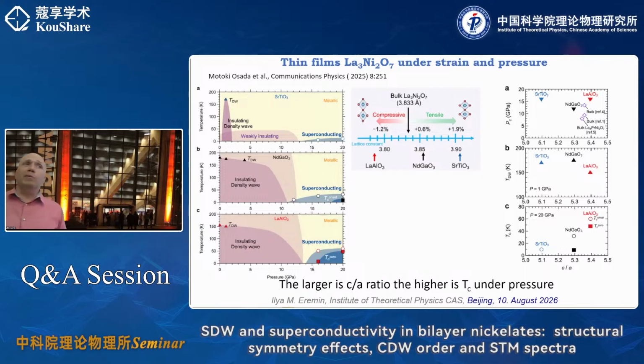In principle, we know that there is a competition here for an unconventional superconductor. It's not unusual that the symmetry may change, because it's always an interplay of the interaction and the fermiology. So it can happen that under compressive strain you get an S plus minus, and maybe for bulk you may get D wave for some reason, because we don't really understand what bulk means. One of the arguments is that we know more or less the lattice constant, but it might be that there is some local stress, local strain. This is what some people argue, and this is where superconductivity takes place. Maybe things change. I don't know.